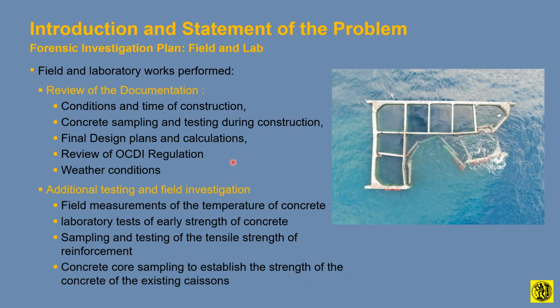So of course we asked to do additional tests. We requested that from then on we do temperature measurements of the concrete during casting of the future caissons, and also have additional laboratory tests of early strength gain of the concrete, and sampling and testing of the tensile strength of the rebars from failed portions of this caisson to make sure that the rebar was okay and ductile. Reinforcing was B500 weldable of high ductility, because this is a standard reinforcement which is manufactured and sold in Greece because of seismic conditions. So, and it was okay.